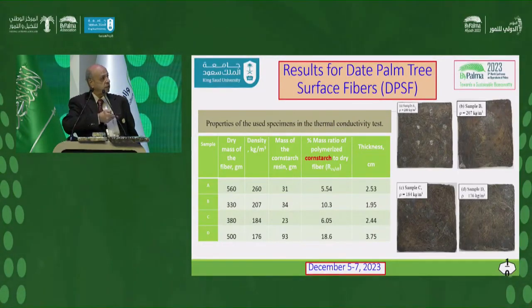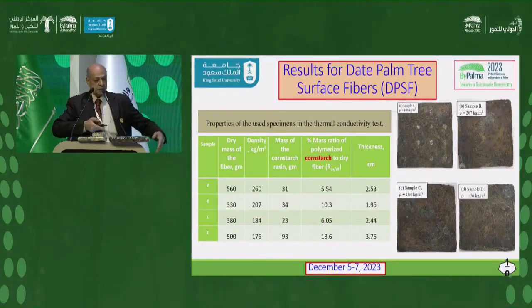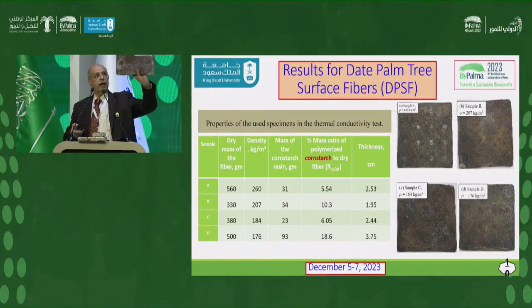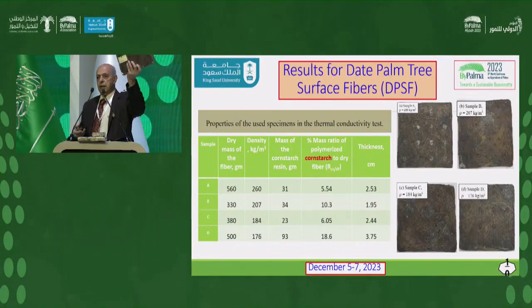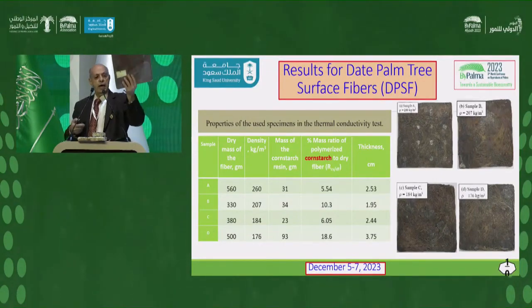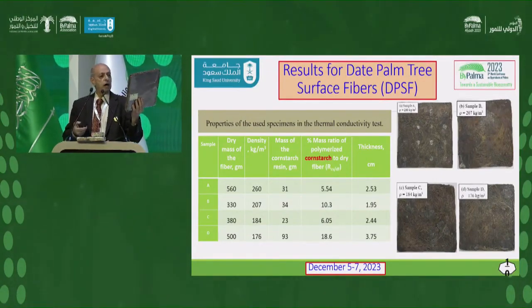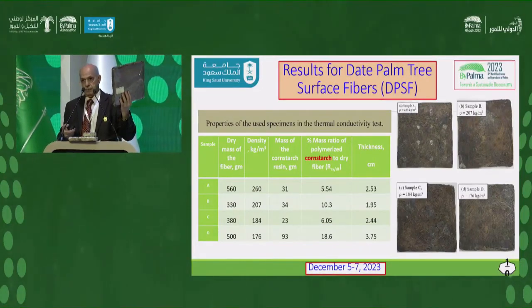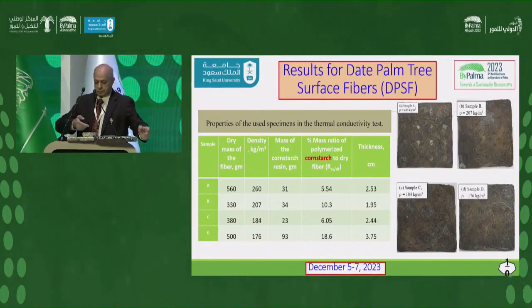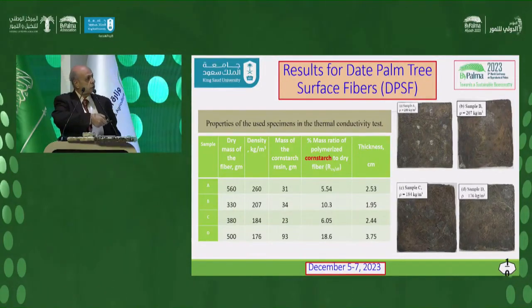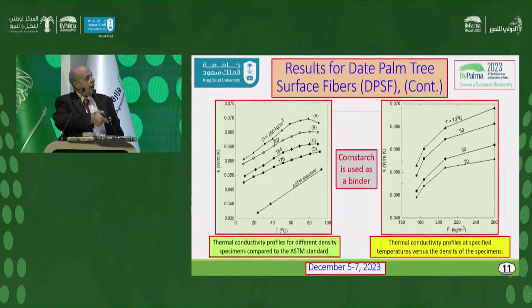This is the percentage of the polymerized cornstarch in the fiber, and the thickness. This is one sample of it, using the cornstarch as a binder, and the thermal conductivity is around 0.05. So these 4 samples have different densities, and this is the thermal conductivity.